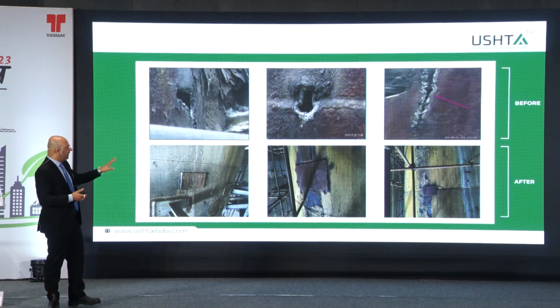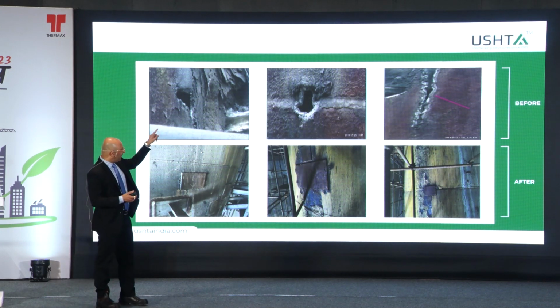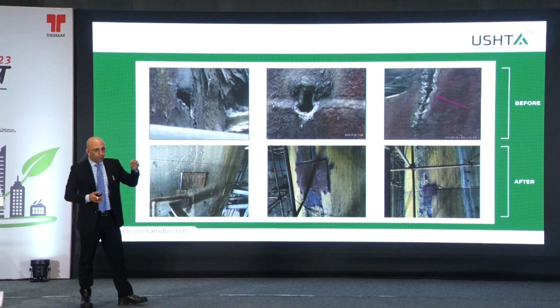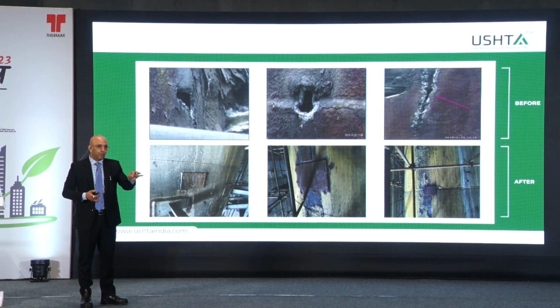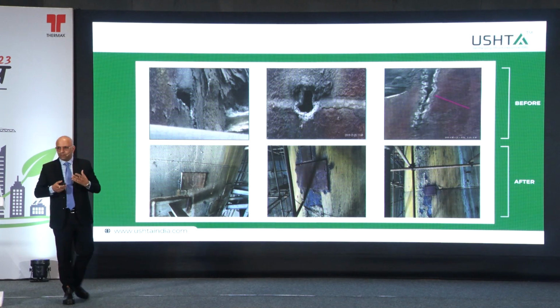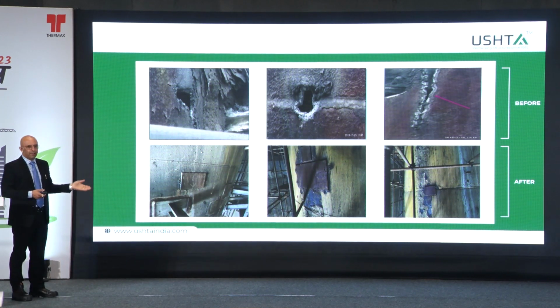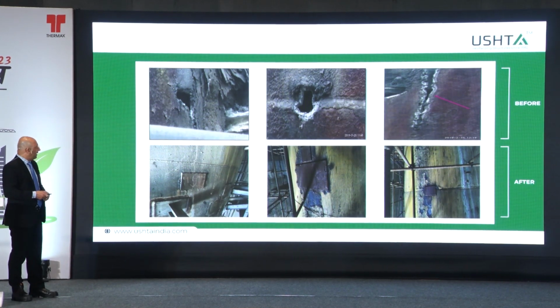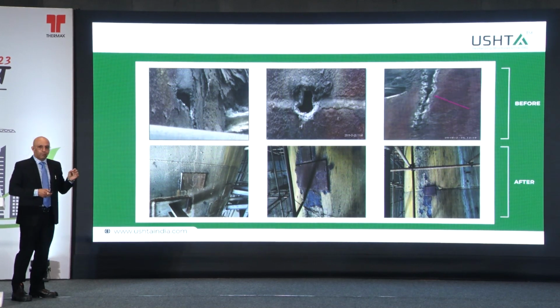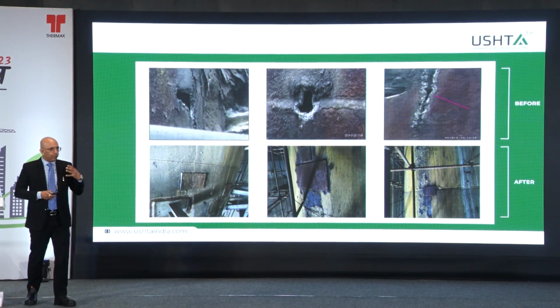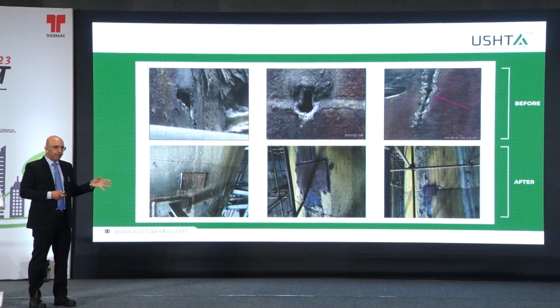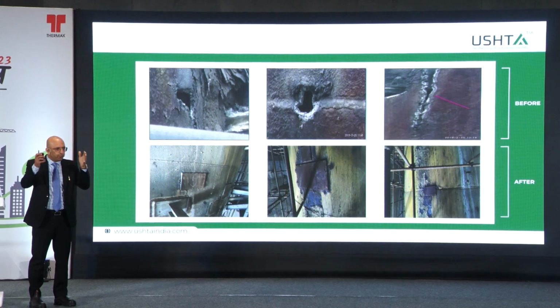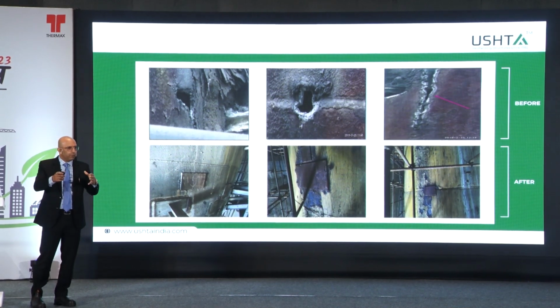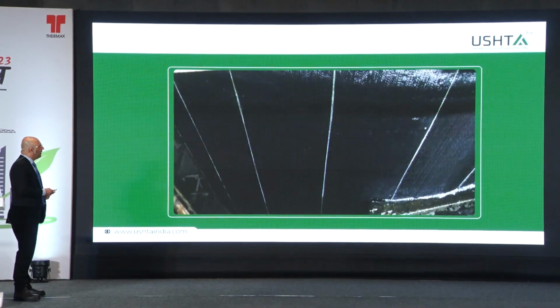And the problem is not only that, these are dangerous gases. If we cut any section, a person working there would die on the spot, so we needed gas masks also, because this is a very dangerous gas. It's a sulfuric acid plant. So there we resorted to strengthening this structure with carbon laminate, isolating that portion, and transferring the entire load from the top to the bottom, isolating the mid portion, and that's how we designed the system.